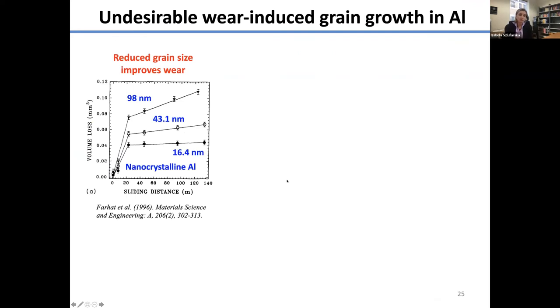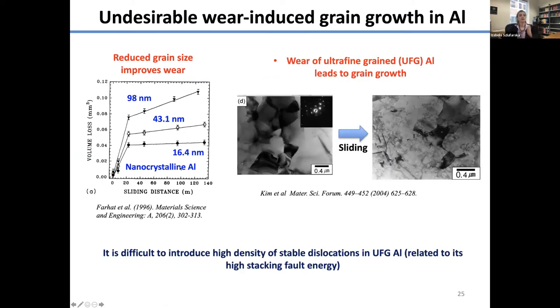Now, one of the ways to improve the wear resistance of metals that I alluded to earlier is to synthesize materials that have nanocrystalline grains. Here's an example showing nanocrystalline aluminum, where this is volume loss, and decreasing the grain size led to improved wear resistance. So this is great. However, the issue is that after prolonged sliding of materials such as nanocrystalline aluminum, many studies have reported that grain growth takes place, and that grain growth eventually decreases the wear resistance. So here's an example of ultra-fine grain aluminum.